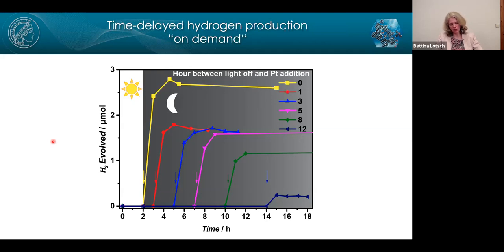So long story short, what we believe is the primary reason here is simply leaking of oxygen into the system. And if oxygen is in the system, then oxygen will act as an electron acceptor. And so this is a likely explanation. I don't think it's the only explanation, because that is something you could control. And I'm pretty sure we have also done other experiments that tell us there might also be other intrinsic recombination, or let's say loss channels, that can contribute to this loss of hydrogen.